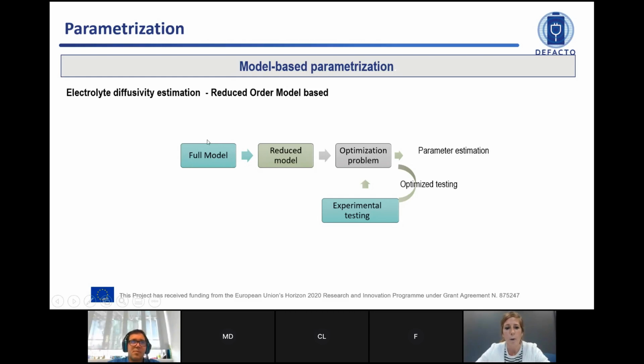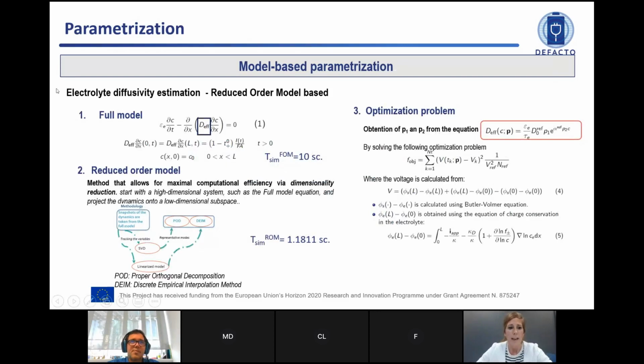So we need to have the full model, then we build the reduced model, and we implement, for instance, quasi optimization problems to first optimize the testing, in order to get an estimation of the parameters properly, efficiently and accurately. So for the case of the electrolyte diffusion estimation and the pulse relaxation method, this is the model for the concentration gradients within the separator and electrolyte. This is the model that we usually discretize with the finite element method in Python, thanks to the FEniCS library, and the simulation takes around 10 seconds, which is not much, but if you want to solve the optimization later, it might be huge.